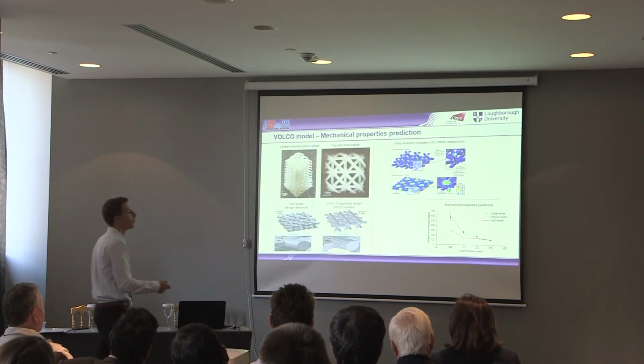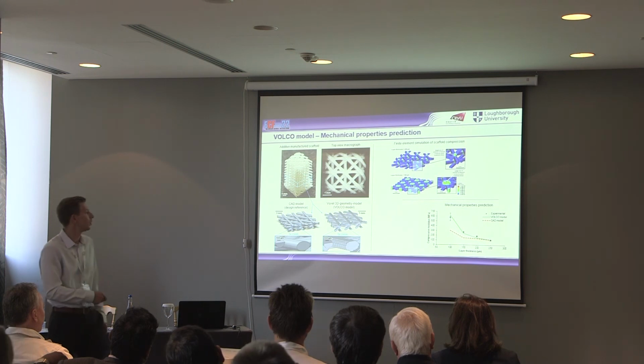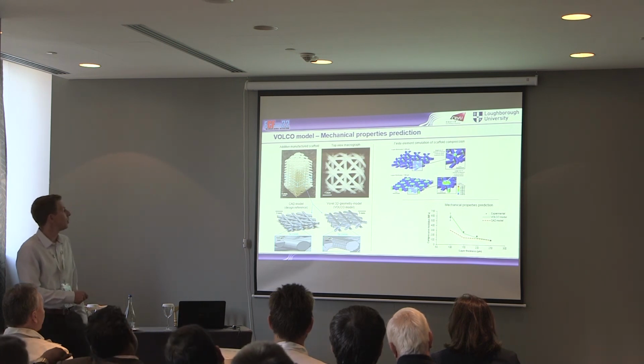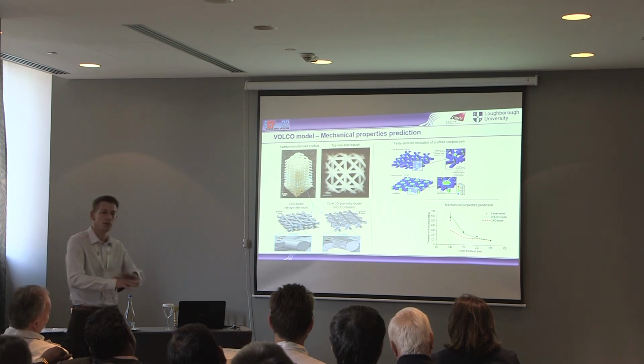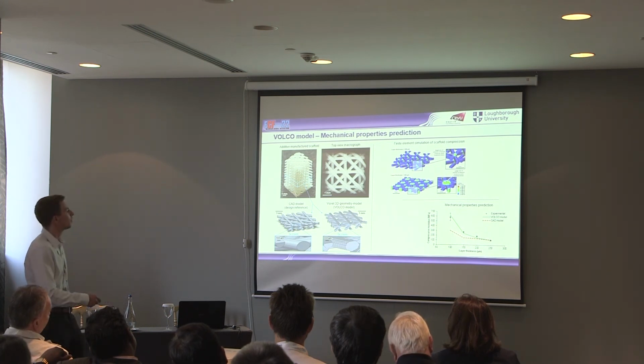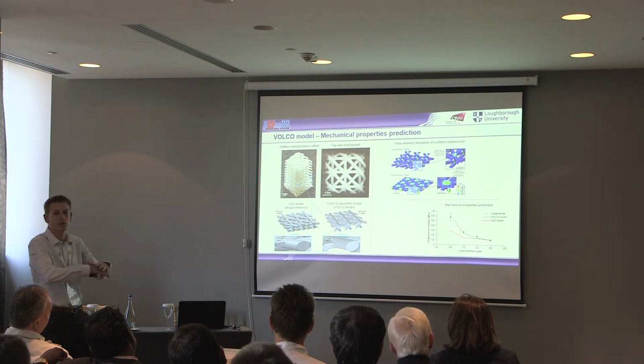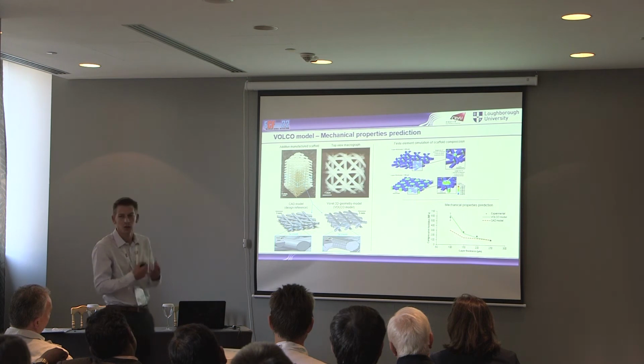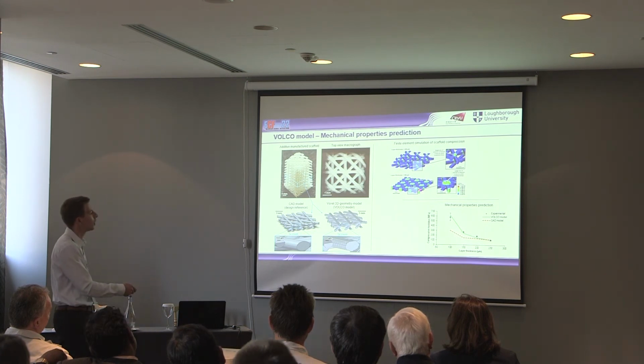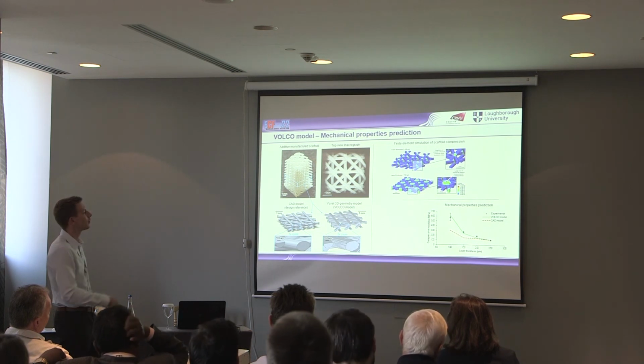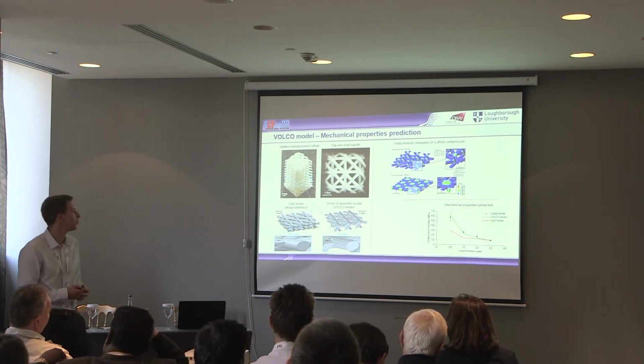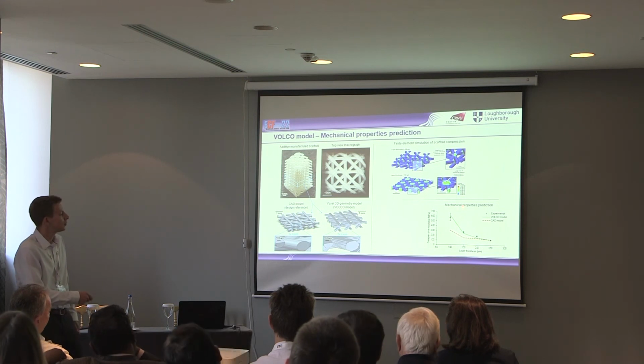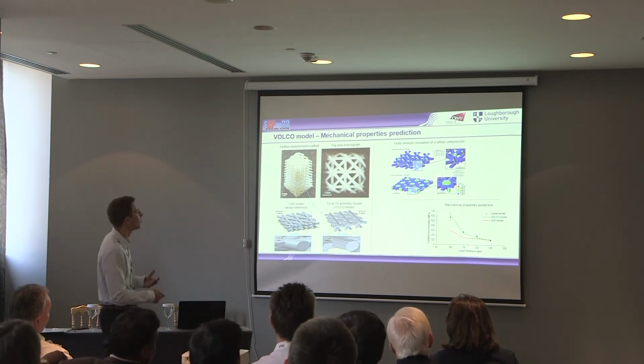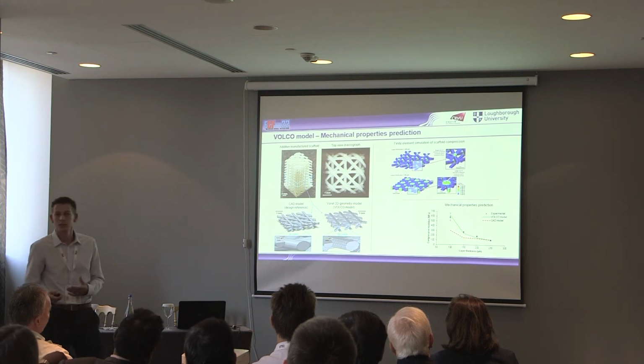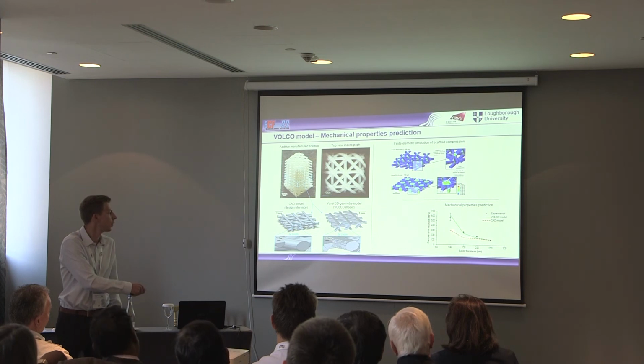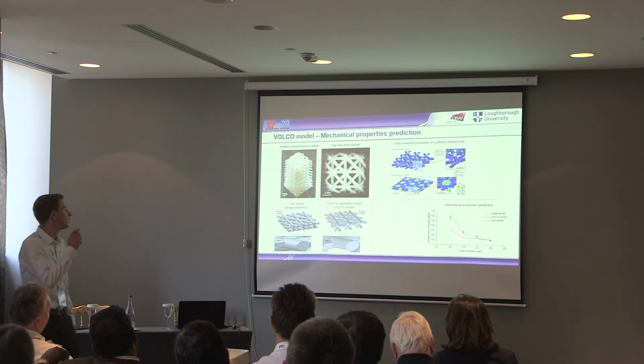So this is the 4 different mechanical properties of 4 scaffolds, the compressive modulus. It's this one, which is 4 layers, with filaments being rotated 45 degrees on each layer, and then for the 4 different ones, we reduce the height of that structure so that the filaments will be printed closer together, so there's more overlap, so the actual overlap between the filaments is much wider than in this one, so the compressive modulus is increasing, and the model is able to fit that trend. Whereas without this model, if you just use the CAD representation of that scaffold, you don't get that at all. This is the results of the predicted modulus. That brings me to the end.